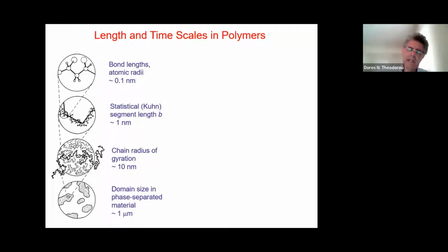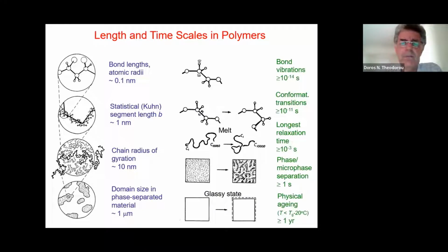We have structure at the level of an entire chain that is quantified by the chain radius of gyration. And for usual molecular weights, this can be 10 nanometers or longer. And we may have phase or microphase separation phenomena in the polymer, leading to domains which may be 1 micrometer or even larger in size. Even broader is the spectrum of characteristic times that we have in polymers.